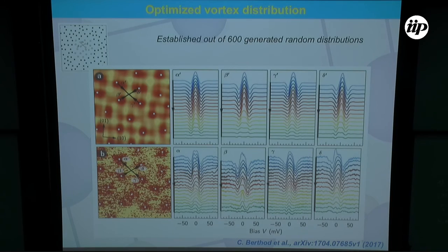So this is the actual measurement with the 4 different traces shown here, after subtraction of the reference spectrum. And this is the calculation. You see the equivalence; although of course the details and the small wiggles from spectrum to spectrum can change, the overall evolution of all these spectra is consistent with the calculation. Okay, so you might say that it's clear that the first spectrum is almost flat at 0 since we subtracted itself in a sense. The traces started here at the center, and we subtracted the same spectrum. So by construction, it had to be flat, with a peak maybe.